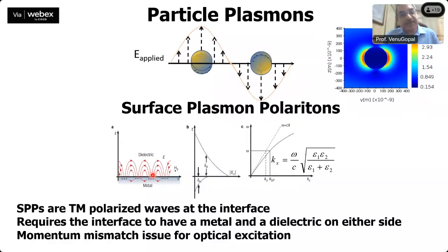So it turns out that the solution shows that it is possible, provided you have a metal and insulator interface, that is, epsilon negative and epsilon positive materials forming the interface, and you have fewer electrons at one place, more electrons at another place. So you have a charge density wave which is propagating along this interface. This is a surface wave by definition, which means that away from the interface, you have an evanescently decaying field. So you're actually confining the field to dimensions, again, much smaller than the wavelength of light.